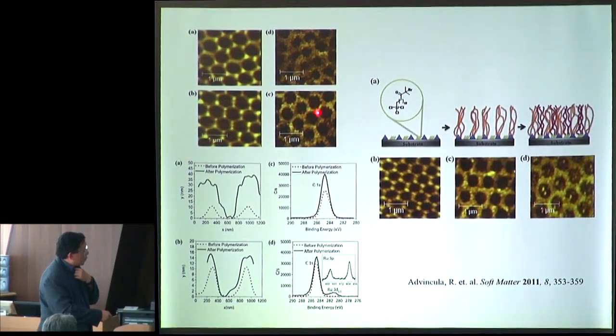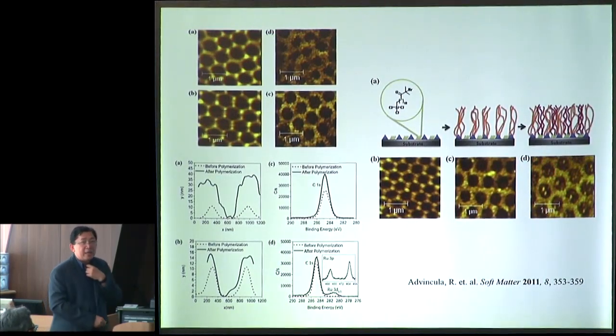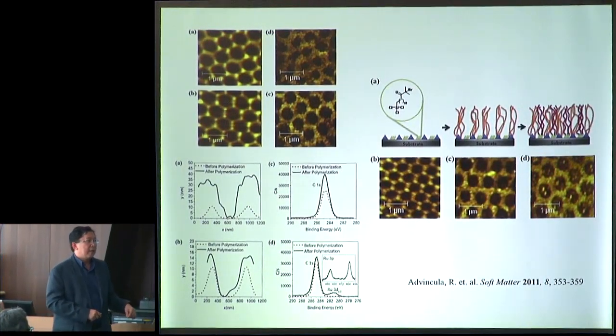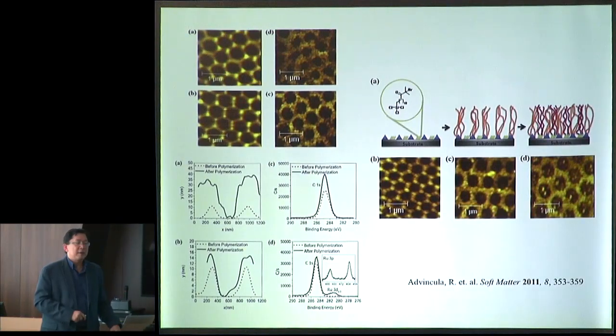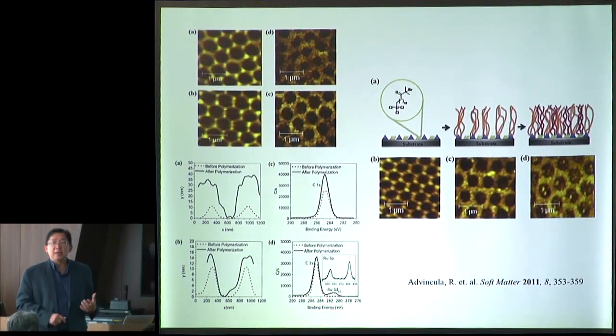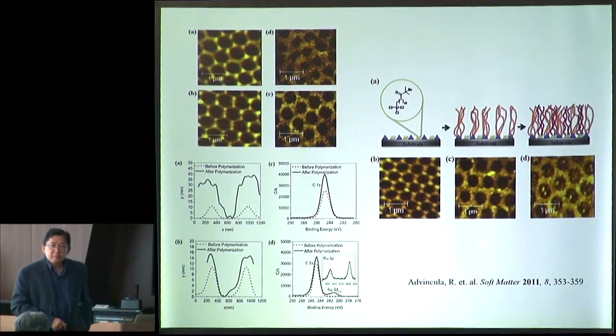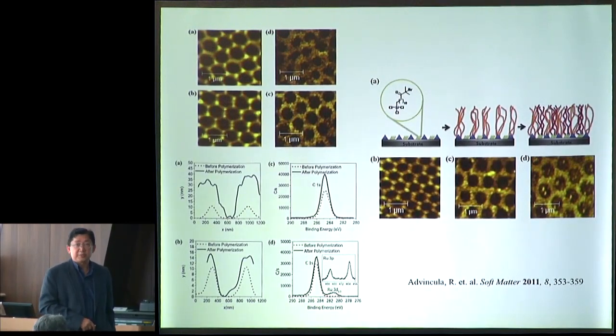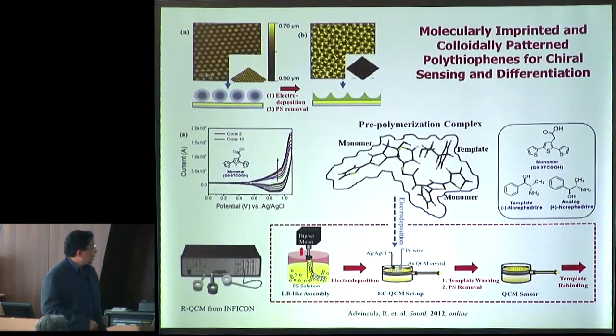Or the middle part, we can grow another polymer brush, and then we can have a brush on a brush. So brush on top of the conducting polymer, and then another brush. So we have polystyrene, poly-NIPAM, or polystyrene PMMA that are distributed, not bicontinuously, but arrayed as a bifunctionality on a surface. Okay? And we've actually used it for sensing.